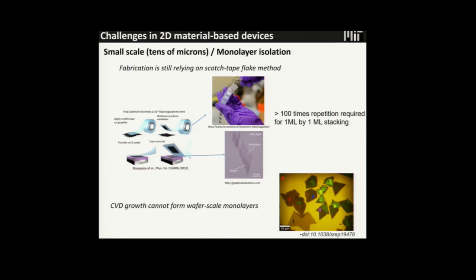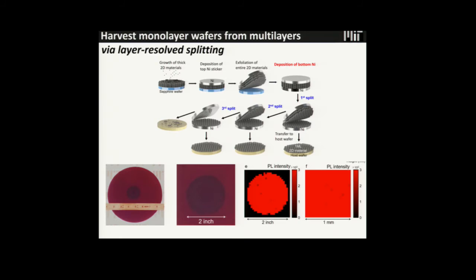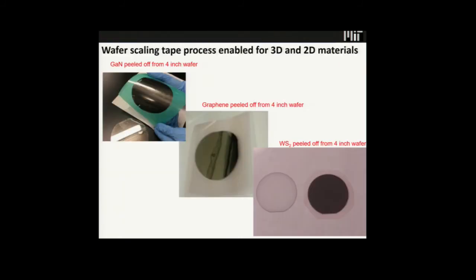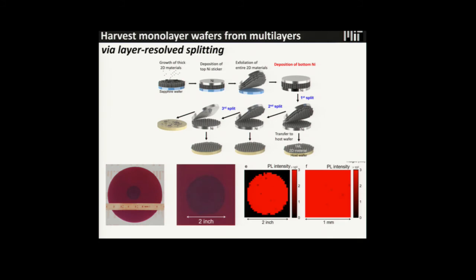So what we try to do for that is as follows. We try to harvest wafer scale 2D materials, very thick 2D materials, into monolayers by using some mechanics. I cannot say all the details about that because it is being recorded right now. This wasn't published yet. But anyway, what we are doing is we grow really, really thick 2D materials on a sapphire wafer. Then we peel off, then we just separate them one by one. As you can see here, this is the 2-inch wafer scale tungsten sulfide separated from the thick tungsten sulfide on the wafer.